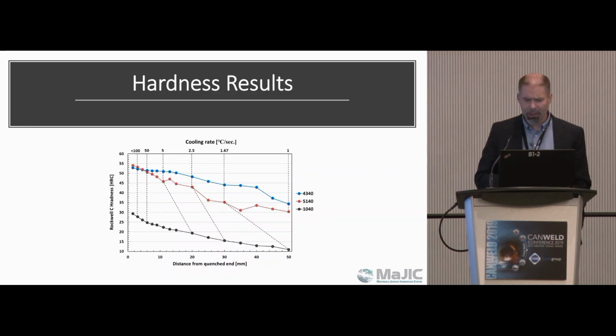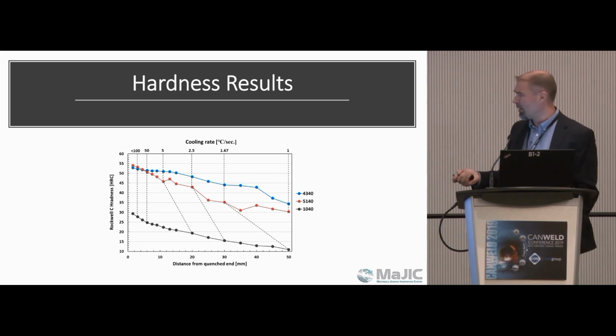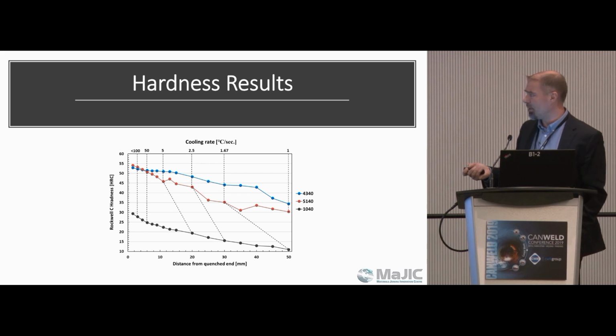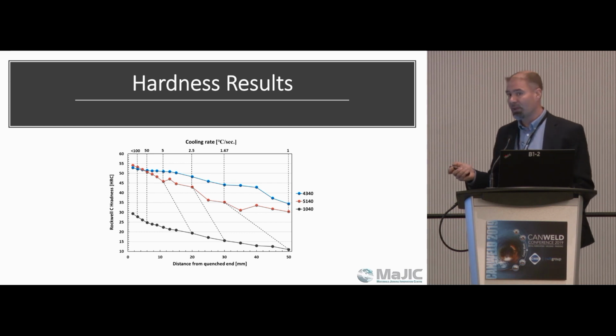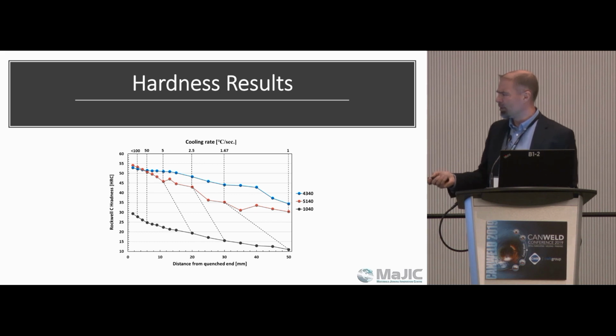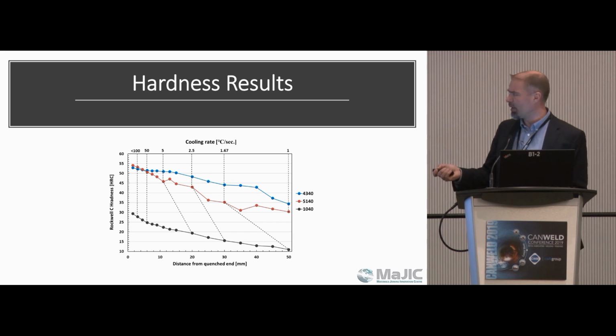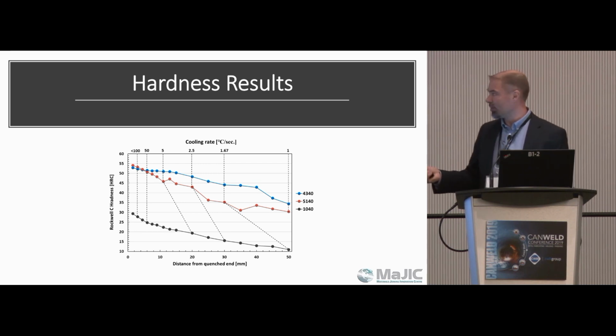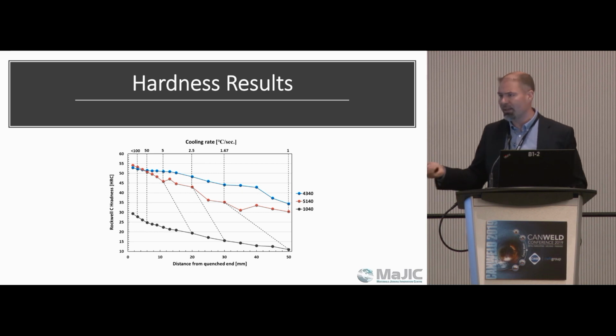So the result here, we had some spurious results with our 1040 steel, but the 5140 and the 4340 showed very good results, correlating the distance from the quenched end to a cooling rate, a very consistent one. We have some good ideas as to why these deviations occurred on the 1040 steel, and so we're going to have to repeat some of that testing. But as we see here, very consistent results with the cooling rates to the end. 4340 steel is a very hardenable steel, so you get this nice flat hardness. As well, 5140, still hardenable, but to a little less of a degree.